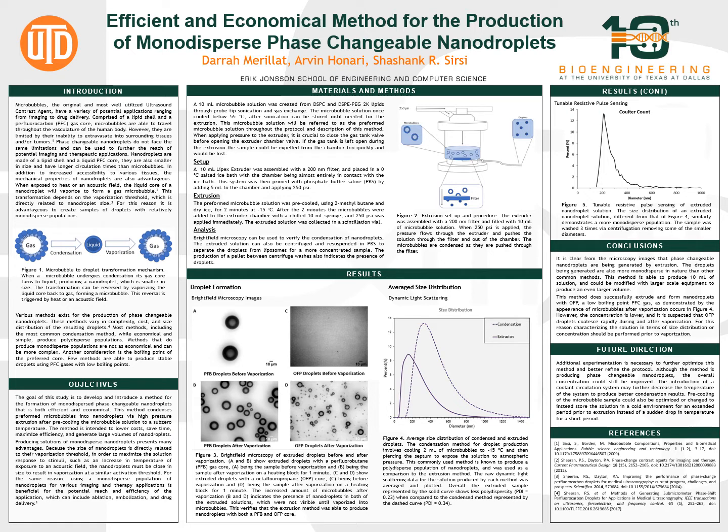Looking into the results section, if you take a look at figure 3 specifically, section B and D, you can see there's much more microbubbles here than compared to A and C. So this implies that after vaporization, these microbubbles that we see here actually came from vaporized droplets that were originally in the solution we collected. So in A and C, they're nanodroplets, then we apply heat, and then we get these microbubbles. So that implies that we did indeed successfully vaporize those nanodroplets originally.